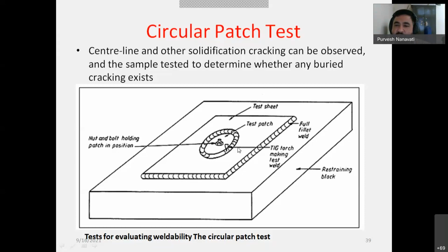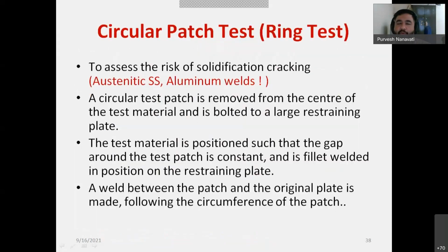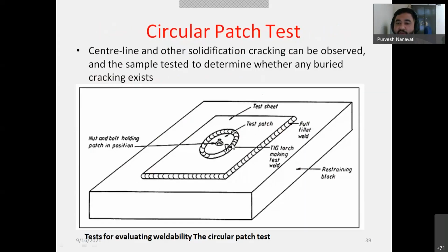Here you can see the TIG torch, right? TIG torch making the test weld. You can see this TIG torch moving around this bolt, and it is producing a test patch on the test plate, not on the base plate. And this is a restraining plate. Now you are producing a restraint condition using this. You are simulating this condition. Now you can understand this test material is positioned so that the gap around the test patch is constant. Because you can see the gap is continuous, right? The gap is constant. From all sides of the test piece, you can see the distance is the same, right?